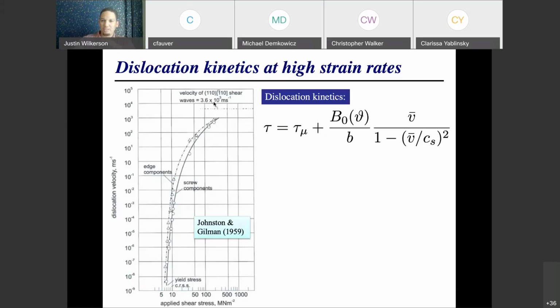So anyways, coming back to our kinetics law here, we have a fairly simple kinetics law that captures this linear regime. So when the dislocation velocity is small, we have a fairly linear relationship between the applied shear stress and the dislocation velocity. And the slope here is given as the dislocation drag coefficient. And then we asymptote towards the wave speed, and that asymptote is accomplished by this denominator here, this 1 minus dislocation velocity over shear wave speed squared.